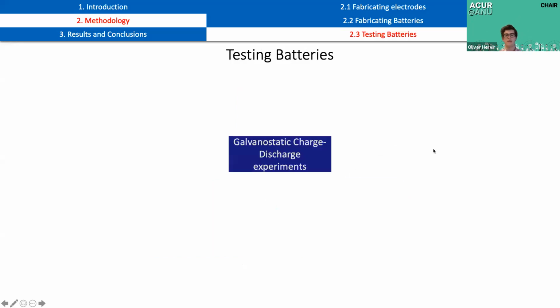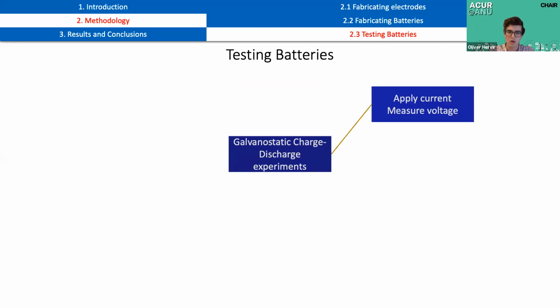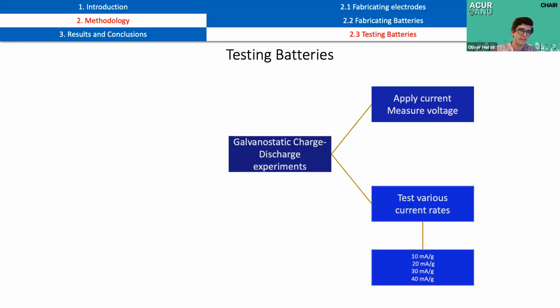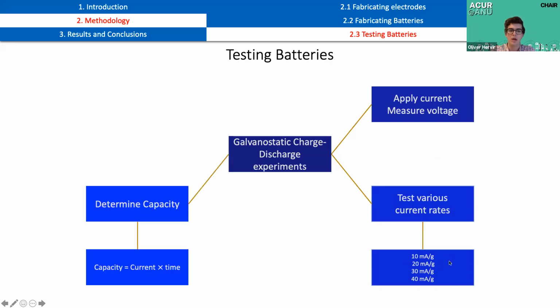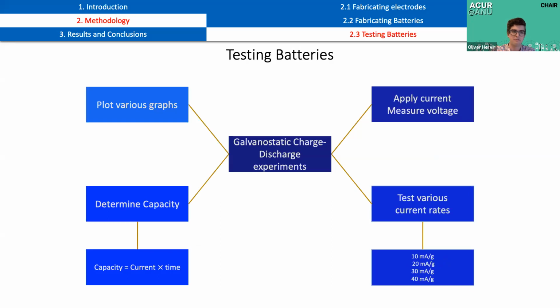So once we've made our battery, we then test it using something called a galvanostatic charge-discharge experiment, where we apply a constant current and measure the response voltage. And we test various different current rates that are all normalized to the mass of the electrode. So for example, 10 milliamps per gram. We can then determine the capacity of the battery by multiplying the current and time. And finally, we plot various different graphs.